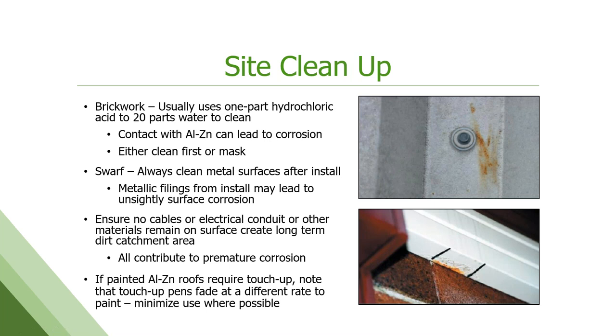Site cleanup. This is the other, as opposed to the galvanic corrosion, this is probably the second biggest complaint I see on new installations. I'll get a call saying, hey, my roof is only 2 months old and it's rusting. Well, it's not really rusting. It's usually because someone didn't clean something else up properly at the site. So this swarf especially. Those are metal filings that occur at the site due to cutting in the field, putting the fasteners in. You get these little shavings of metal that fly around everywhere. If you don't clean those up, they stick to the surface and they start to rust.